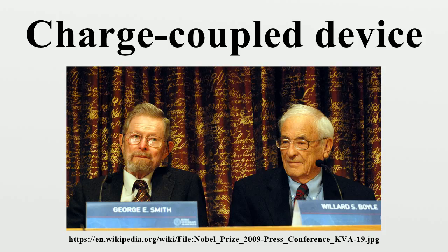The gate oxide, i.e., the capacitor dielectric, is grown on top of the epitaxial layer and substrate. Later in the process, polysilicon gates are deposited by chemical vapor deposition, patterned with photolithography, and etched in such a way that the separately phased gates lie perpendicular to the channels. The channels are further defined by utilization of the LOCOS process to produce the channel stop region.